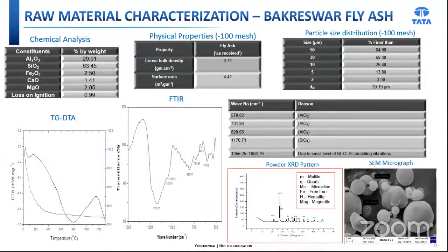Chemical analysis of the fly ash also reveals a high percentage of both silica and alumina with low content of iron oxide, lime, and magnesia. The analysis confirms that impurities are within reasonable limits and will not badly affect the properties of the derived reaction sintered mullite compacts. The particle size distribution analysis demonstrated that 70% of the as-received fly ash is finer than 30 micrometers, and the average D50 value is 30.19 micrometers.